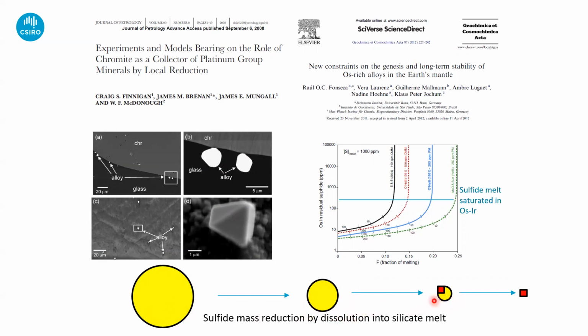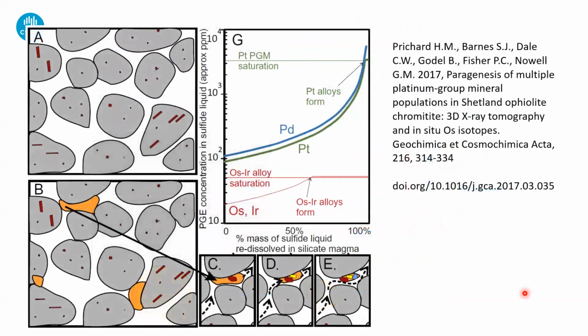What that does is it increases the IPGE concentration in the sulfide. And when it gets up to a few hundred ppm, that's enough to stabilize these phases. And then if the sulfide then completely melts and disappears, then you leave behind these phases in the mantle. And these are the things which are the basis of rhenium osmium model ages in mantle rocks. So that's what we thought might be going on here.